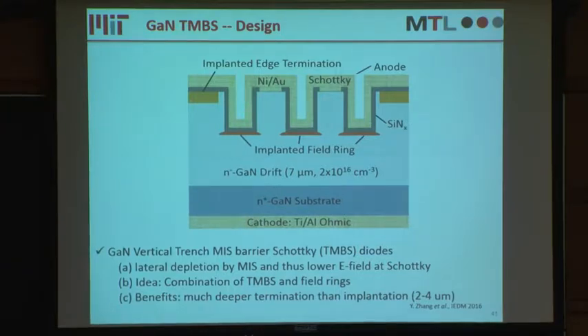So basically, we form a metal insulator and semiconductor MIS barrier at the sidewalls and the bottoms of each trench. We also implanted some field rings at the bottom of each trench.